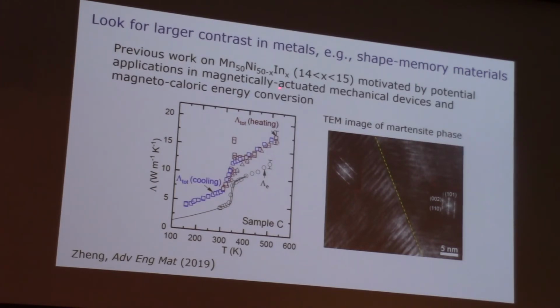And it's been used in lots of other kinds of science. This is what we measured. So this is the thermal conductivity of this material. At room temperature, we tuned this composition to make that change occur near room temperature. And it's a little bit better than a factor of 2. So the thermal conductivity increases by about a factor of 2 at a phase transition. It's a martensitic transformation, a martensite, an austenite phase.